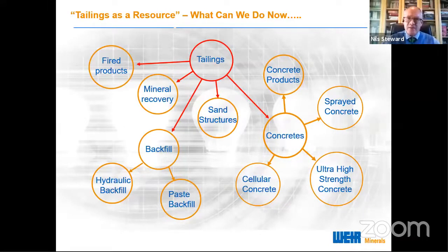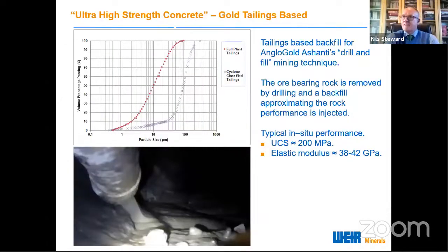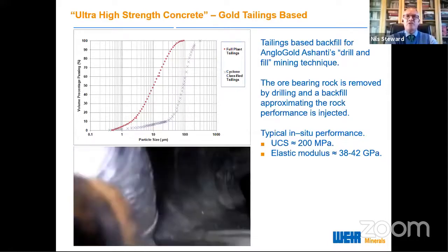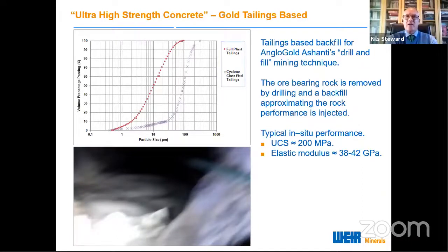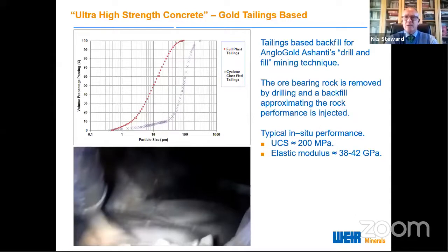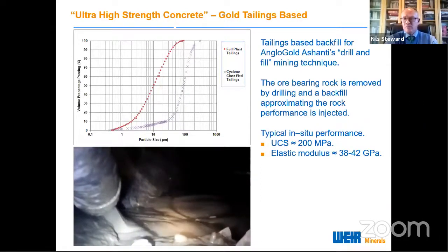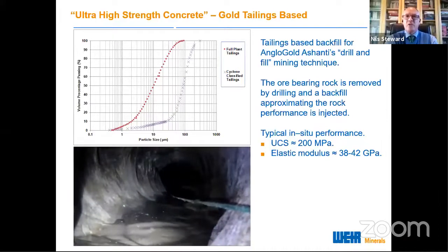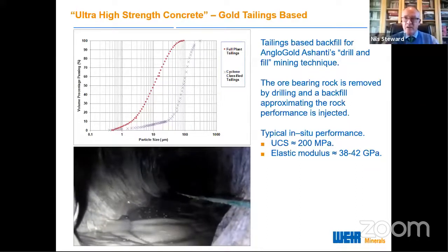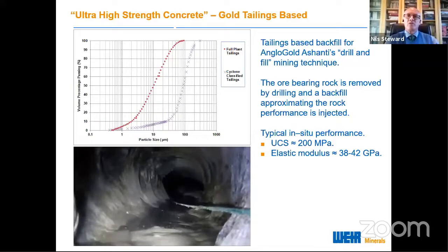Now, it's easy to talk about it, but what's actually being done? If we have a look at this particular product, it's my personal favorite. This is a product that was produced out of mine tailings for the AngloGold drill and fill mining technique in South Africa, where what they did is they drilled out the gold reef. So they would drill a hole between 500 and 900 millimeters in diameter at a dip of around 20 degrees and over 30 meters. So you would remove that rock, basically just taking out the gold channel. And what they wanted to do was replace that with essentially rock. So they wanted a cement product that gave around 200 MPa UCS, uniaxial compressive strength, and an elastic modulus of 38 to 42 GPa.